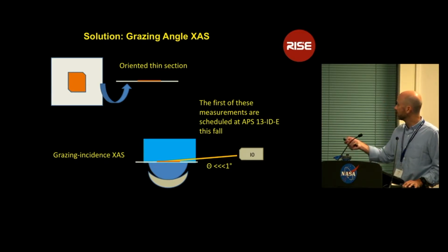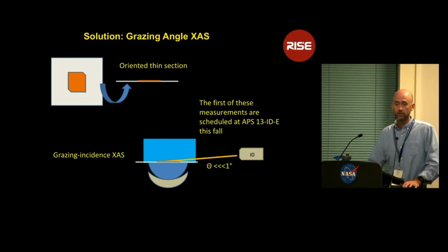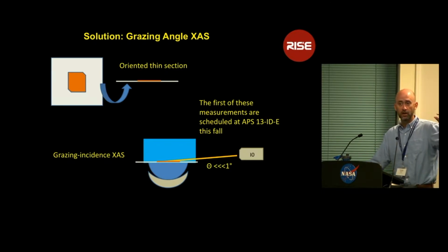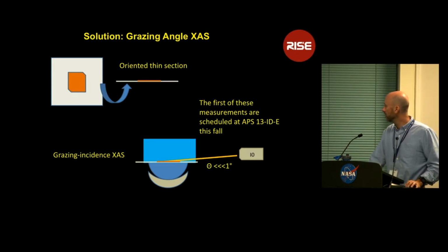We're going to orient our thin sections and do grazing angle measurements. And these are measurements where we do the X-ray absorption spectroscopy with an incidence angle much, much less than 1 degree. Here we can be sensitive only to the top 100 or so nanometers of the sample, and we should be able to get a really precise and accurate measurement of the change in oxidation state of the upper layer of our sample after both irradiation and impact.